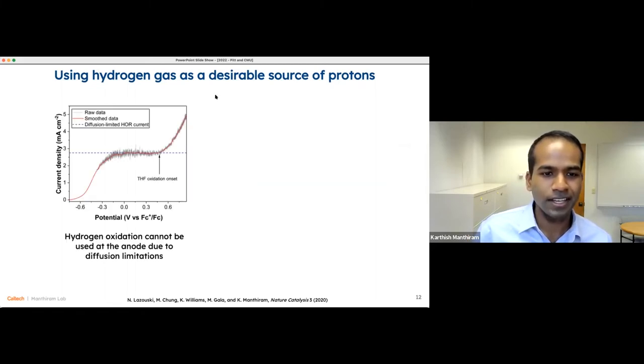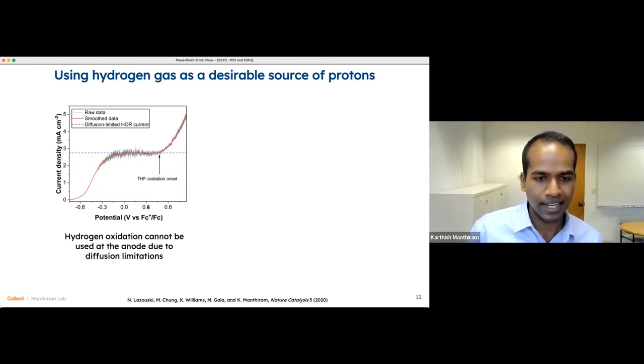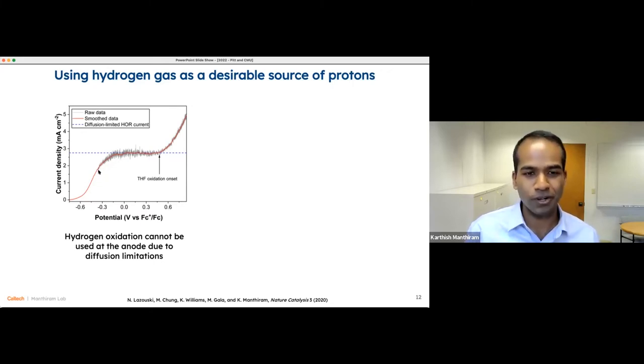So it's important to see what happens on the other side of the cell as well, what happens when it comes to the hydrogen oxidation. So here on the left-hand side, we have the potential on the x-axis that we're applying. Going to the right, we're applying more and more oxidizing potentials. And we have current density on the y-axis. You'll see at first that the current increases as we're oxidizing hydrogen. But eventually, in a flooded system, we have a transport limitation. So the current plateaus out. And then as we go to higher overpotentials, we start to oxidize THF. And so this is, of course, exactly what we want to prevent.